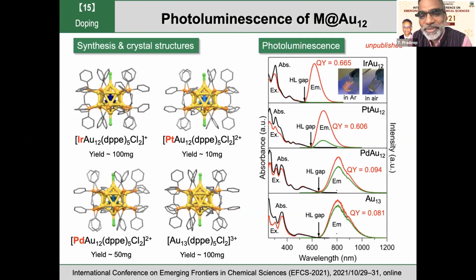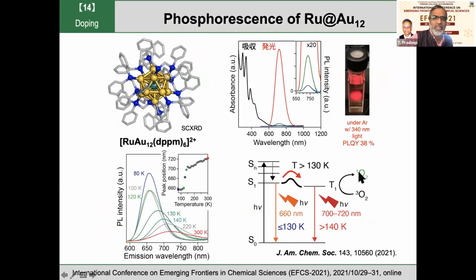But I wanted to know what your thoughts are. Also, the oxygen binding. Do we have a bound state of the clusters with oxygen? You mean the... we didn't see the complex of oxygen and the clusters, for example, by using ESI. So the binding is not responsible for the photoluminescence response you talked about, the sensitivity and all that. So, is there any transient state possible? Yeah, oxygen. We observe the formation of singlet oxygen. So energy transfer is very efficient from the T1 state of the clusters to triplet oxygen. So this quenching is very effective.